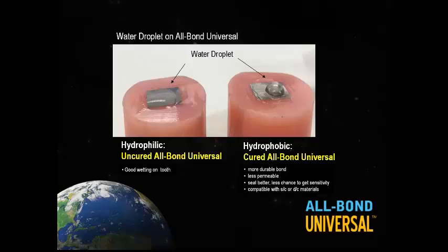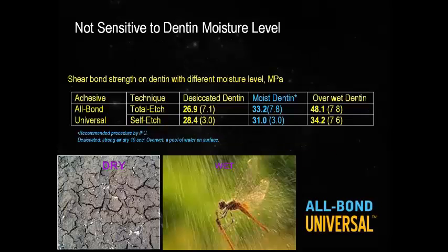And the study done by Bisco shows the bond strengths on 3 different types of dentin. One that was completely desiccated, one that was moist, and one that was over wet. And as we can see, the bond strengths are pretty high and pretty within each other's range. And what does that tell us? That it doesn't matter what surface you apply All Bond to, whether it's dry or wet, depending on the type of bonding technique that you like to use, you're going to get a good bond strength to the substrate that you're bonding to.